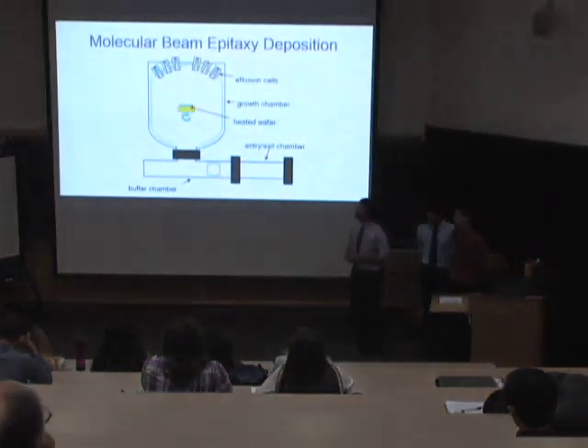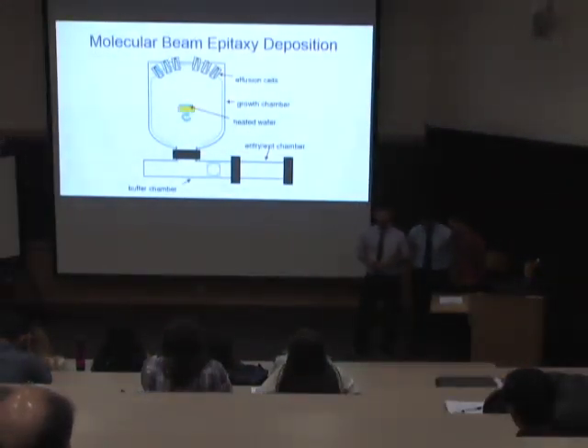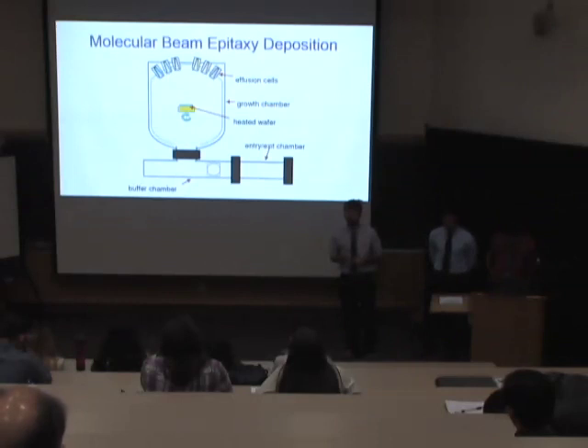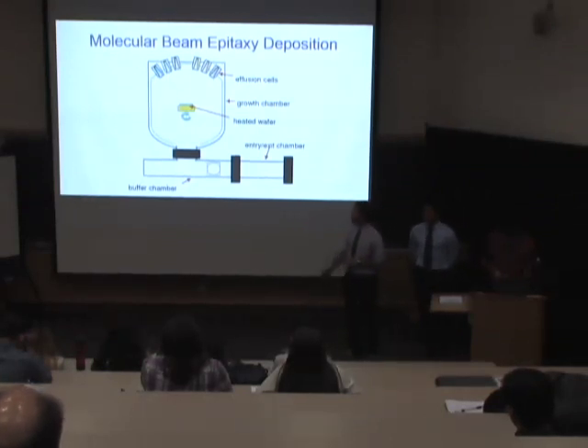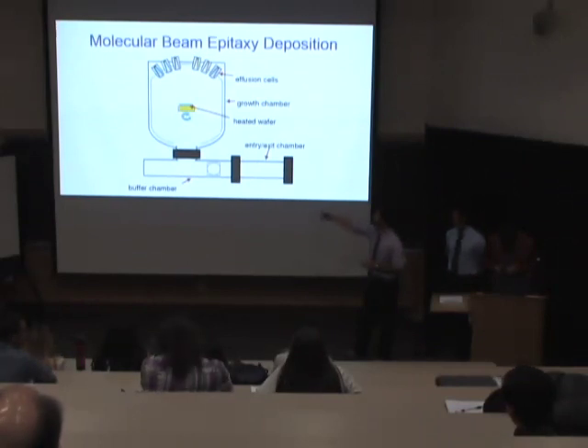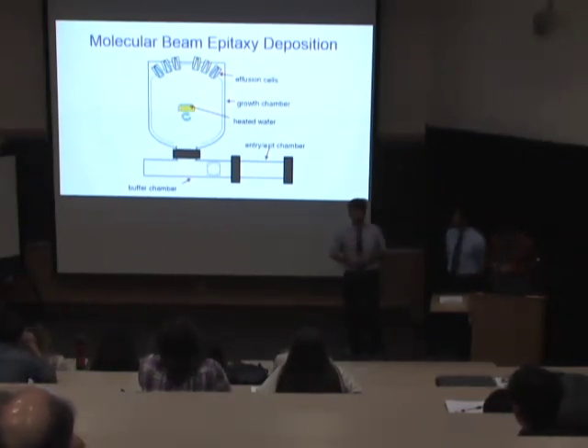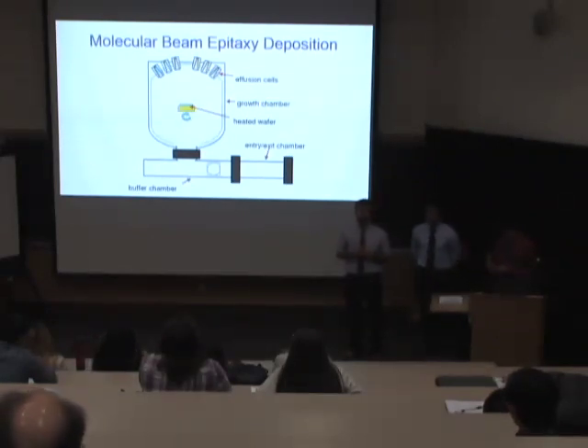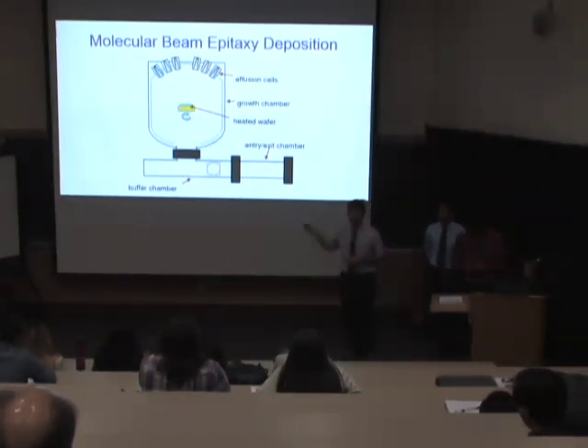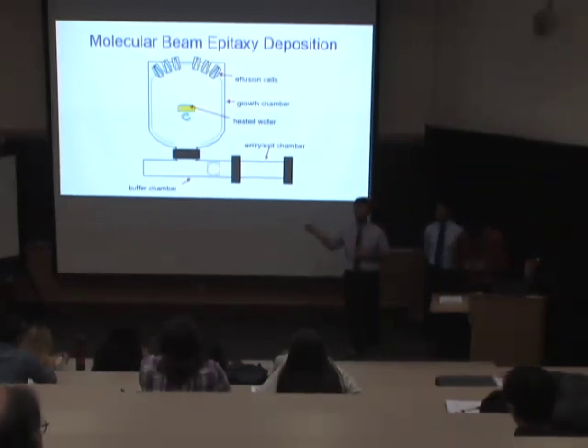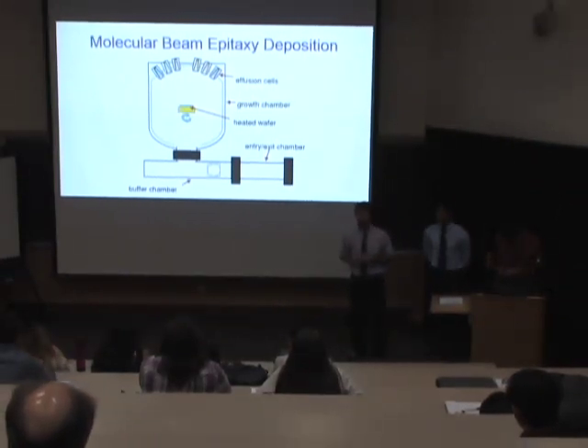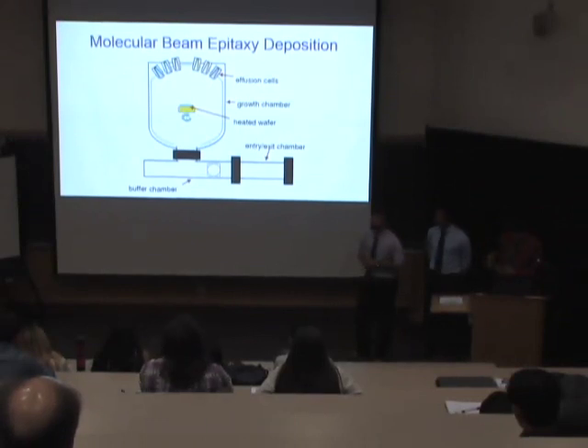This is a diagram of what an MBE does. MBE is important for this type of research because we need clean and pure ways of growing thin films without any sort of contamination. How this achieves that is within this chamber and actually the whole system, the pressure is 13 orders of magnitude lower than standard ambient pressure. So ambient pressure is what we're feeling right now. 13 orders of magnitude lower exists within this chamber, meaning it's one of the lowest pressures on this Earth that's even achievable. And from within this system, we can then ensure that there is no sort of contamination that's going to enter our thin film as we grow them.